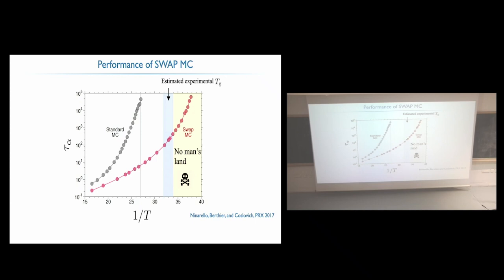And you see that this is really dramatic, because if you were to extrapolate this up to way longer, 10 to the 12, you would get here. So this is the estimated experimental glass transition. You see you completely break this glass ceiling, as people call it, and you can go even below. So this has been something quite recent. You see 2017, where Andrea Ninarello, Ludovic Berthier, and Daniele Coslovich really put the right type of model with all this optimization to get this speed up.